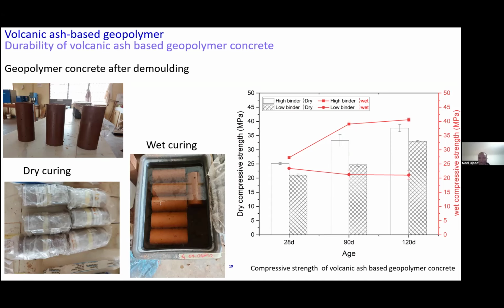So to make sure that the product is still sustainable and available for anyone, we try to check two mix designs: a mix design where we have a high binder content, and a mix design where we have a low binder content, to check how those mixes behave in those different climatic conditions.